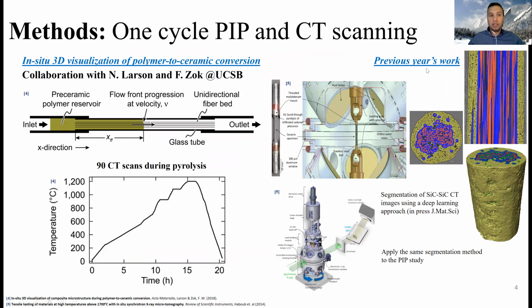So before I get started, this work is built on experimental studies that were done as part of a PhD thesis by Natalie Larson, advised by Professor Frank Zok at UCSB. And what Natalie did, she focused on studying or visualizing polymer to ceramic conversion. And one of her experiments in the synchrotron involved infiltrating a fiber bed that is surrounded by a glass tube. So she can do in-situ pyrolysis, so she can pyrolyze these polymers in the fiber bed up to 1200 C and cool them down over the course of 20 hours.